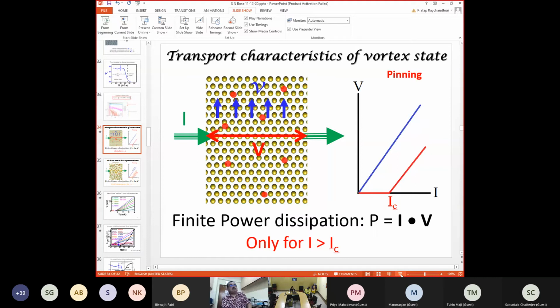Now if I have a vortex fluid, in that case, these few pins can never block the motion of all the vortices, because this is like putting an obstruction in a river. So therefore what will happen is that even at very low currents, I will start having a dissipation, but that dissipation will be much smaller than if it was unpinned, because I have this obstruction which is hindering the flow of vortices. And then at, of course, high current, I will have a finite slope.